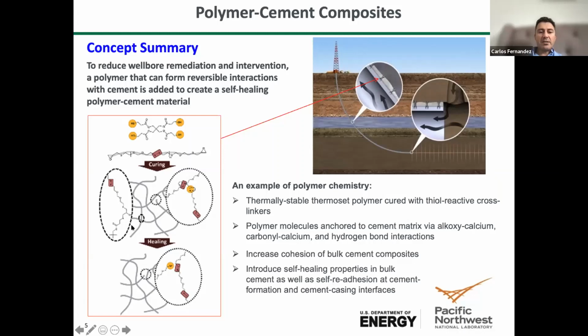So there is a mechanism. For example, here, this is a thermoset with sulfur-sulfur bonds in the backbone of the polymer. And that sulfur can exchange with other sulfurs in the polymer. During that exchange, if you have a fracture in the polymer itself, the polymer can mobilize and break this bond, and this has to happen with heat. So it is thermally activated, and then forms a different bond, another sulfur-sulfur bond, to bridge that fracture and heal it again. So it's not just a simple self-filling mechanism, but true self-healing, because you form a chemical bond at the fracture and restore the structural integrity of the polymer.